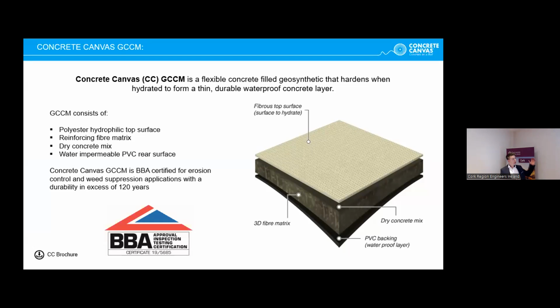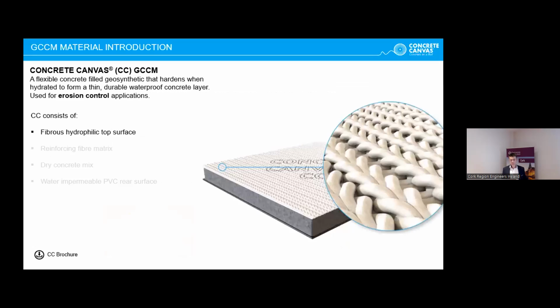Just to let everyone know, it's designed for non-structural erosion control applications, and it's certified by the British Board of Agrement for a durability lifespan in excess of 120 years for erosion control and weed suppression applications. So it has long-term durability. The top surface is your fibrous top surface. In the field, this acts hydrophilically, so this is the section of Concrete Canvas that you should hydrate in the field. It wicks in the water very quickly, but it's also tight enough to contain the dust and the cementitious fill within the material. So there's a very low washout rate, less than 3% within the GCCM material.